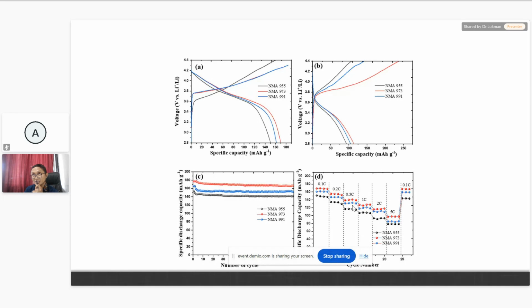If we compare to commercial NMC like NMC 811, the specific discharge capacity of this sample, especially NMA 973, is still below the commercial NMC. For NMC 811, the specific discharge capacity is around 200 milliampere hour per gram. So even though our discharge specific capacity is lower than NMC, there is still a chance in the future to improve the electrochemical performance to achieve higher values than right now, and research is still going on to improve this capacity or to reach a goal at least similar to commercial NMC.